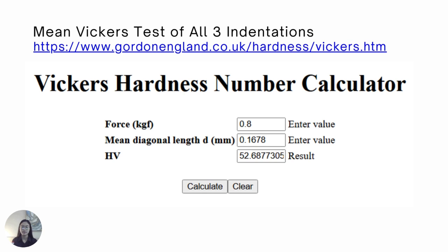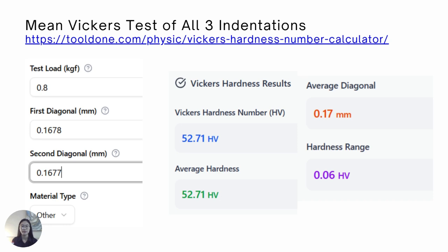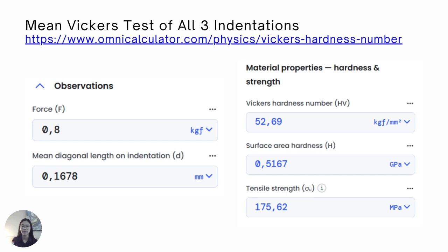Now this is the mean of all three indentations of the Vickers test. So the force is still the same, 0.8, but the mean diagonal of all three combined is 0.1678, making the HV average 52.6. And then we input the same into Tooldone, all three indentations, getting the results of 52.71. And then lastly, Omni Calculator also resulted the same, which is 52.69 or 52.7. All three calculators gave consistent results, allowing a final mean hardness value.